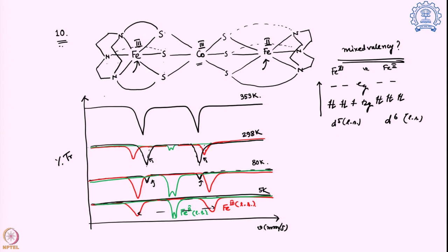So over here you can see how they are behaving. That is how iron 2 and iron 3 come out. For the iron 2 low spin system, the valence contribution would be 0, so the valence electric field gradient will be 0. The lattice gradient will be there because there are 3 sulfurs, 3 nitrogens, so that remains the same for both of them. But in the case of Fe3 plus, you can see there is an imbalanced charge distribution. So the valence EFG will not be equal to 0, and the lattice EFG is already not equal to 0.